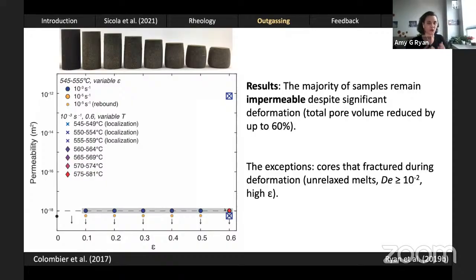The exception, of course, are the cores that fractured during deformation. You can see those noted here with X's, while the remainder of the data are plotted down here at the limit of the apparatus I use to measure permeability, which is 10 to the minus 18. I'll remind you that fracturing only occurred in unrelaxed melts, so those deformed above Deborah numbers of 10 to the minus 2, and only at high strain, or usually at high strain.